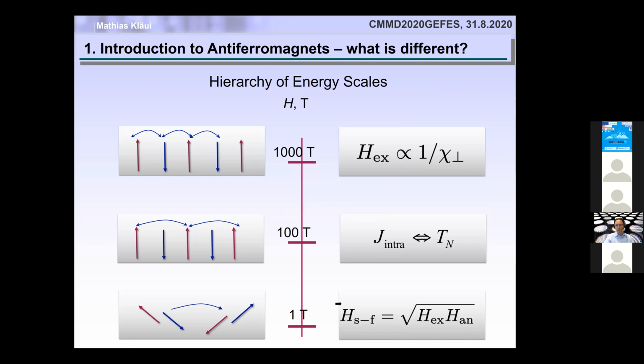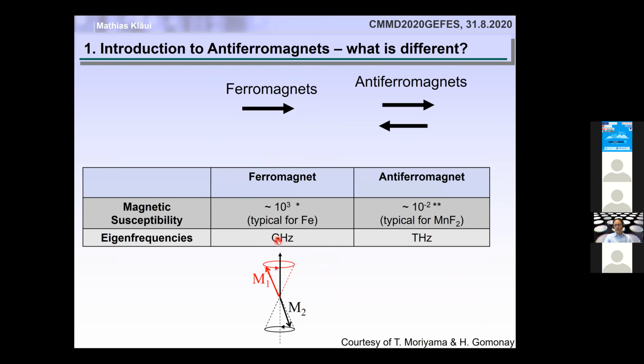And finally, the only temperature scale, the only field scale where we can actually do something in the lab easily is the anisotropy that sets this so-called reorientation of the sublattices. So that is something where we can actually work in the lab, whereas these two are so strong that usually we cannot access these in the lab. Now, this very strong coupling between the two sublattices also leads to the fact that the eigenmode frequencies are a couple of orders of magnitude faster in antiferromagnets than in ferromagnets, leading to this very exciting dynamics in the terahertz range.